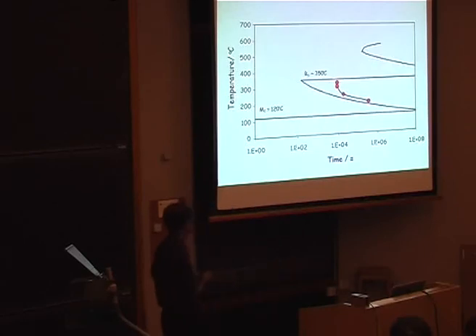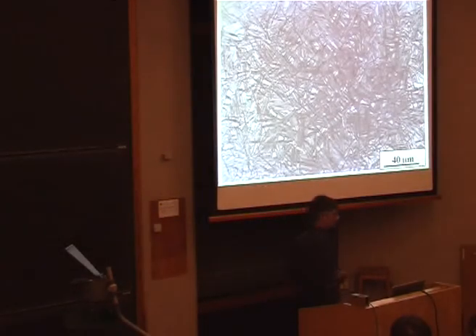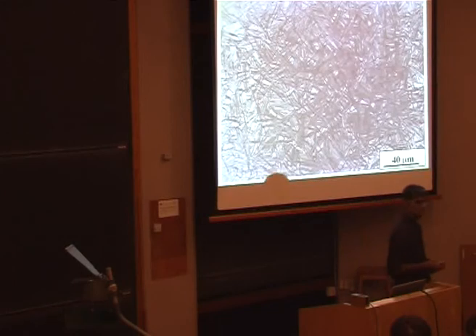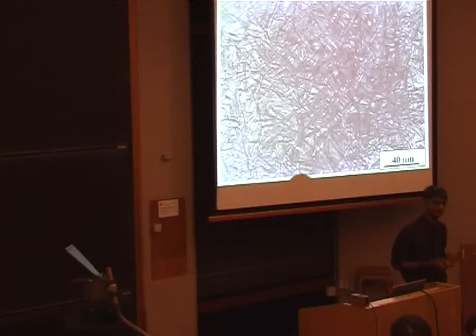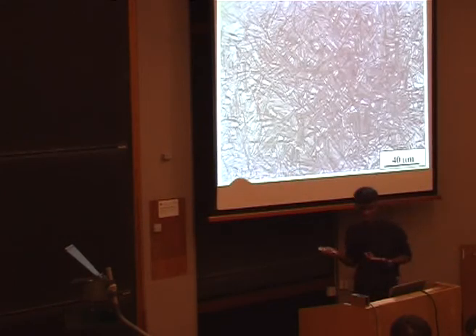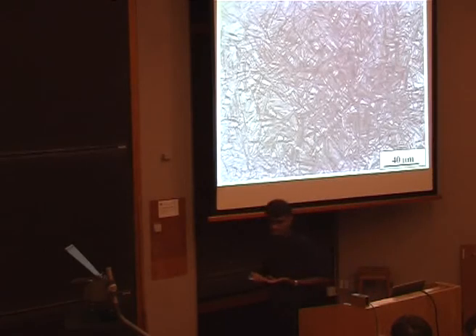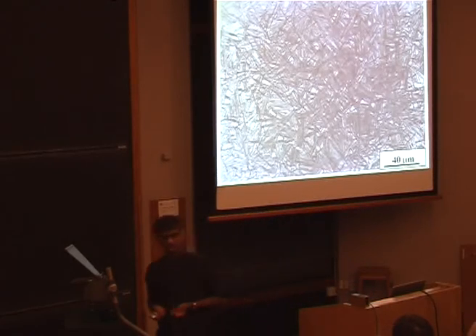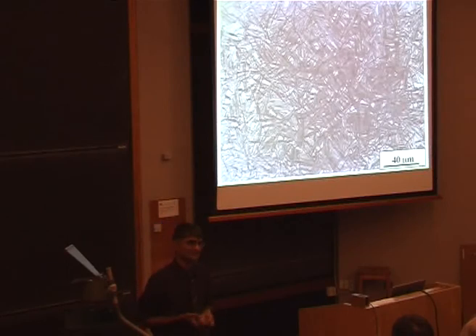And this is just to show you the calculated time for transformation versus the measured time. And this is a structure that we get, optical microstructure. Nothing remarkable about this. You must have seen many micrographs like this. There's nothing here to indicate that we've achieved the nanostructure scale, etc. But I want you to watch the next slide. I think, in my opinion, it's the best transmission micrograph ever taken.